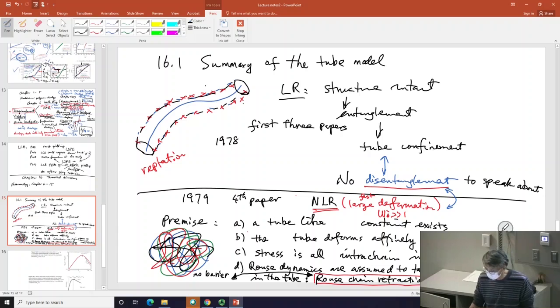So the question was, what do we mean by barriers? From our observations, in the simplest case, you have an entangled melt, you make a filament, and you draw it to, let's say, double the length. That turns out to be about enough. Hold it, and it will break up. But if I only go 50% of my length, it doesn't break apart. So there is a barrier. Or, if you like to see that failure as disentanglement, there's a barrier against that disentanglement.